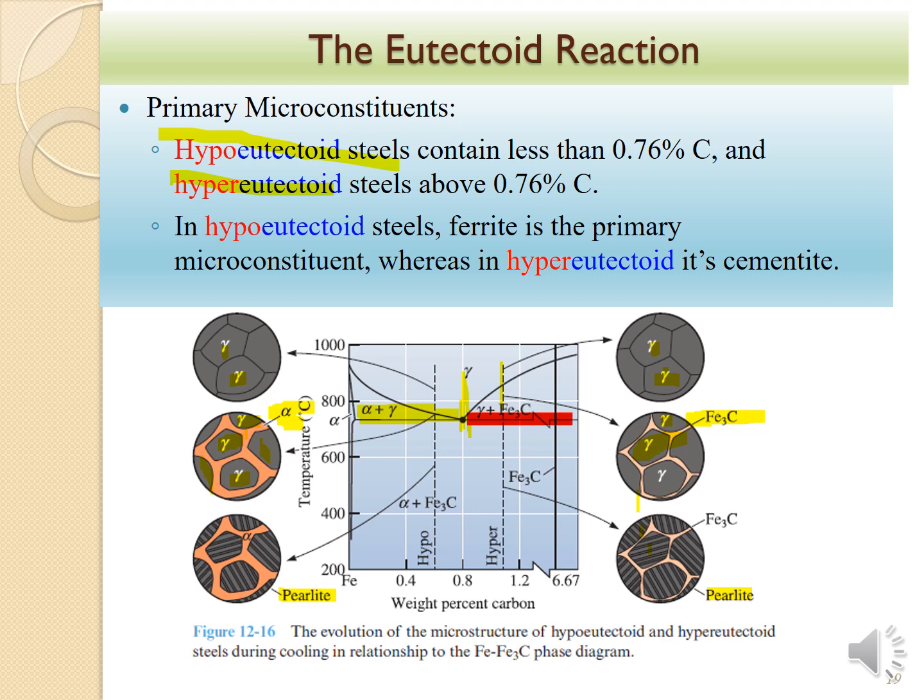Although below the eutectoid temperature we only have two phases, the alpha phase and the cementite phase, the microconstituents can be different. On both sides of this eutectoid composition, we can have pro-eutectoid alpha plus the layered structure pearlite, or we can have the pro-eutectoid cementite plus the layered pearlite.